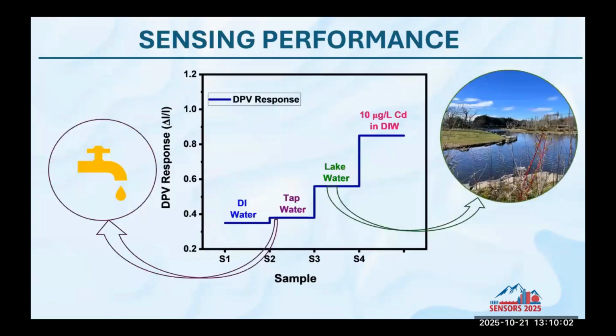And also, we tried to use this sensor on real samples. This is our blank sample, DI water, which has no ions. This is the response with DI water. And then when we check it with the tap water, there's a slight increase in the response. This is because water in itself has some minerals or salts present in it. So there would be a slight change.